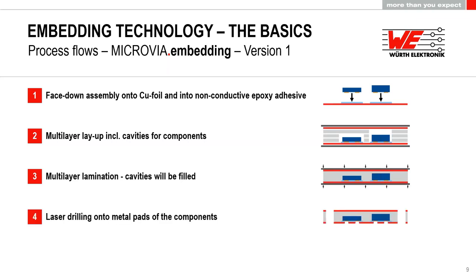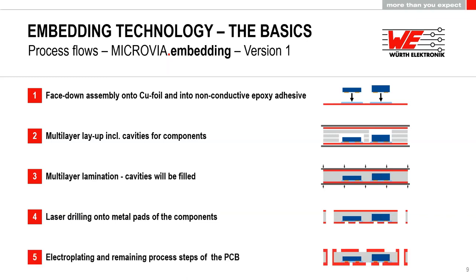And then we go to our drilling processes, and especially the laser drilling is of interest here because we drill down through the copper, through the epoxy adhesive, onto the metal pads of the components so that later in the electroplating process, we can contact the component directly with copper.